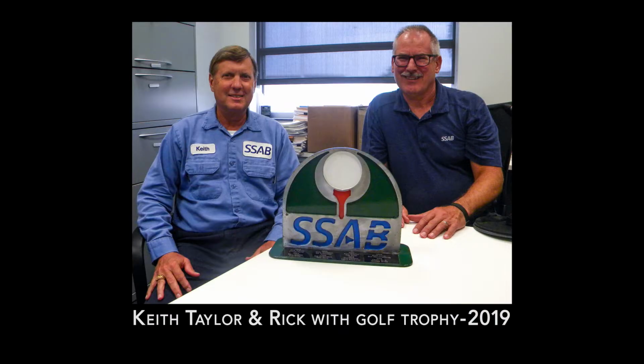Also improved the toughness of the chromoly V turbine rotor by adding a substantial amount of nickel and some niobium for grain refinement. So we had a finer grain size, and we improved toughness very much. It had pretty good embrittlement resistance. Keith Taylor and I prepared a paper on medium carbon bainitic steels, and it was published in Iron and Steelmaker. I think probably one of the best papers on bainitic steels, and I don't know that a lot of people know about it, but one of the works I'm most proud of.